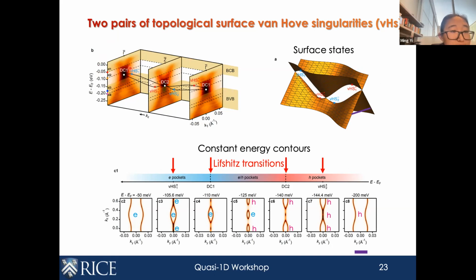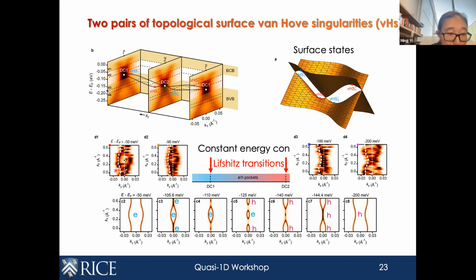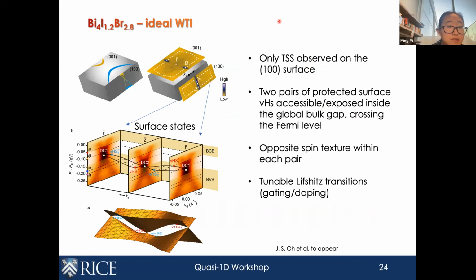It's feasible to achieve the doping of the system to realize these types of evolution. So experimentally, we can also cut at different energies to see that the constant energy contours indeed are consistent with the warping produced by this model. Therefore, we really think this iodine 1.2 and bromine 2.8 is an ideal weak TI because it's stable over all temperature scales that we can observe, and the topological surface states are completely exposed.